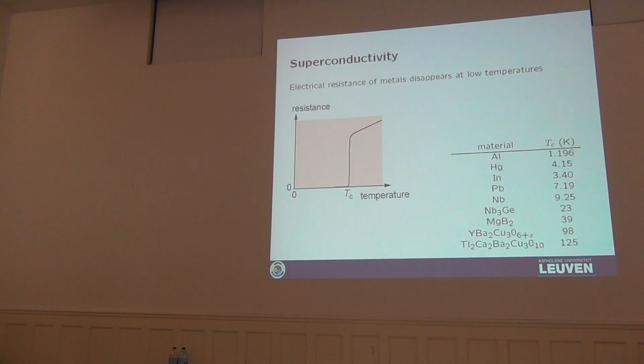All right, so that's actually the discovery itself. And you see that it looks simple to detect it experimentally by measuring resistance as a function of temperature. And then very interesting experiments were performed to detect what the resistance still is here. The best way is to inject a supercurrent in a superconducting ring and then to measure it constantly as a function of time, hoping that it will start sooner or later to decay.